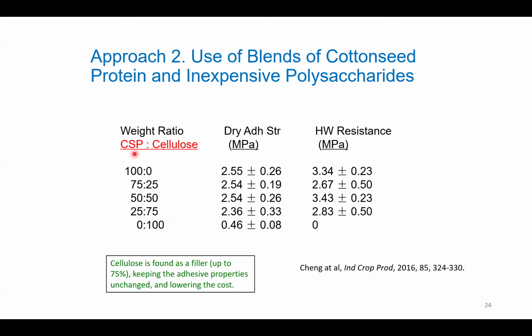Cottonseed protein, 100% cottonseed protein, has this dry adhesive strength and this hot water resistance, these two values. If you're blending the cellulose up to 75%, you can see the values don't change that much from the original value, which means that cellulose is found as a filler up to 75%, keeping adhesive properties unchanged and lowering the cost.